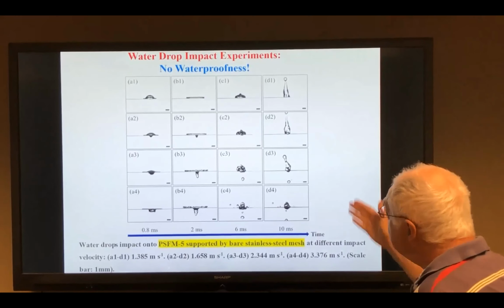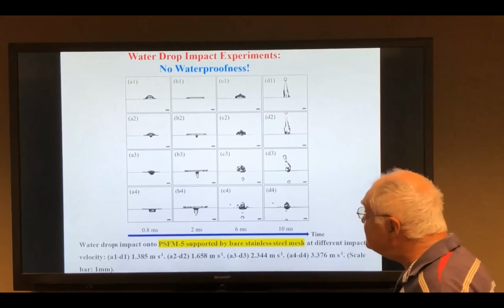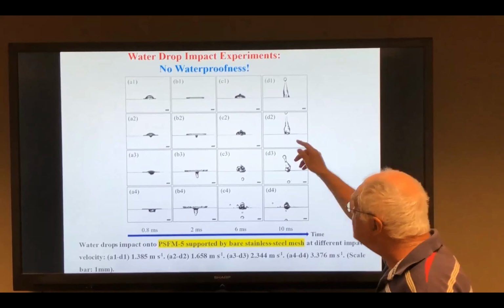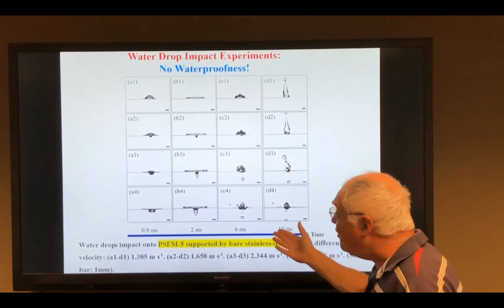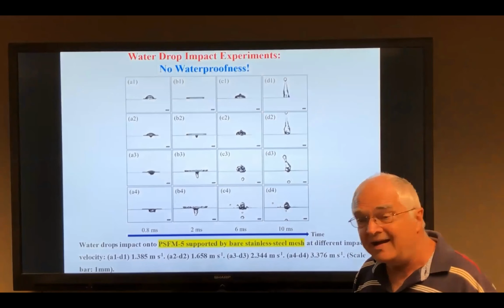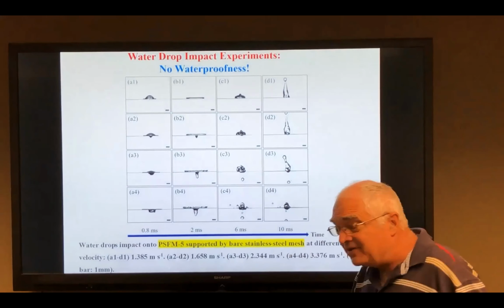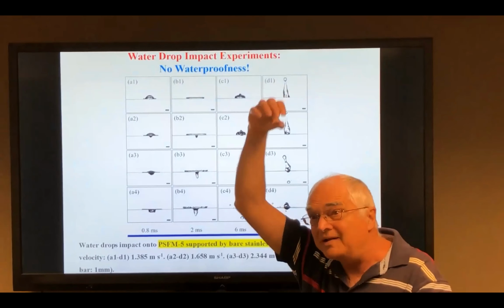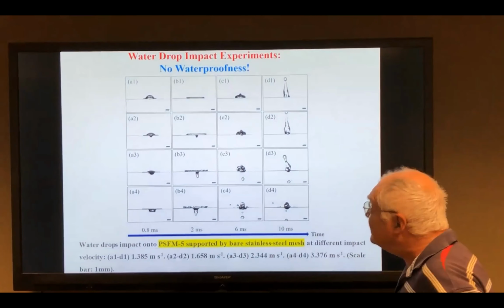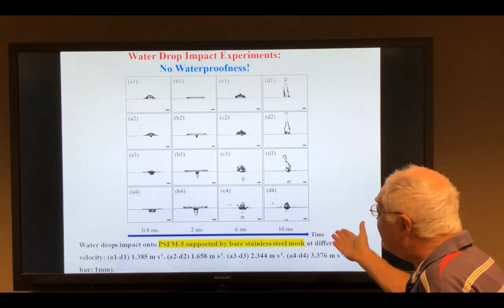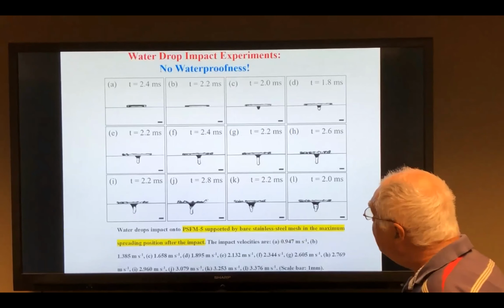At the higher speed, you see that our membrane suddenly appears to be not super hydrophobic, because water goes through, so it doesn't protect. There is a dramatic difference between the softly located droplet and a droplet dripping. So what's the reason for that? This is not a waterproof membrane then. Please go ahead, the next one.